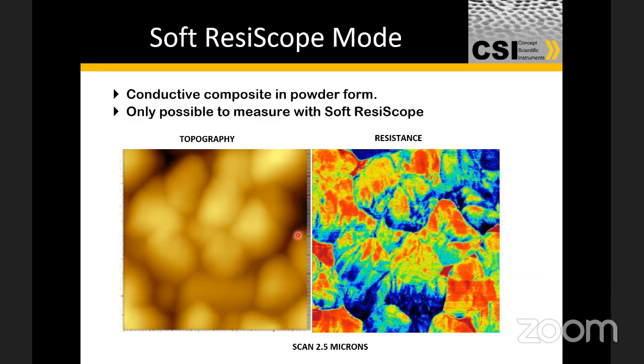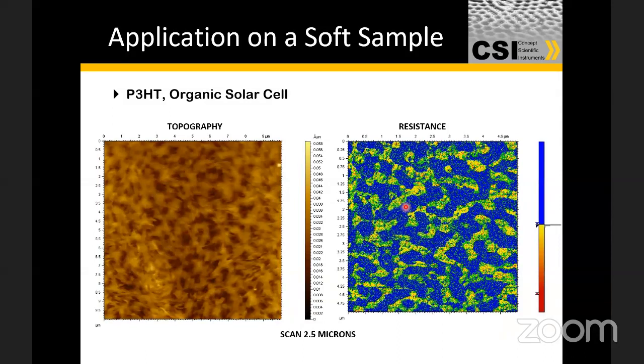So each of those grains here, you see, I guess, about 500 nanometers. So the resolution you're looking at, again, is down to about 500 nanometers. And again, another example. This is a very nice example for P3HT, a very common organic solar cell material, as you know. We're just trying to illustrate the nice clean measurements that we're able to get on something like P3HT. So for those of you who are working on organic solar cells, we really think that we have the best solution in the market today for making these measurements.